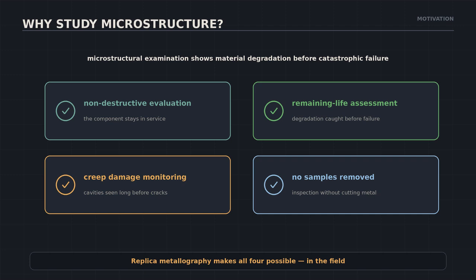Why look at microstructure at all? Because long before a component fails catastrophically, the material tells you it's degrading, if you know where to look. Replica metallography gives you a non-destructive window: remaining life assessment, creep damage monitoring, and inspection without removing a single sample. The component never leaves service.